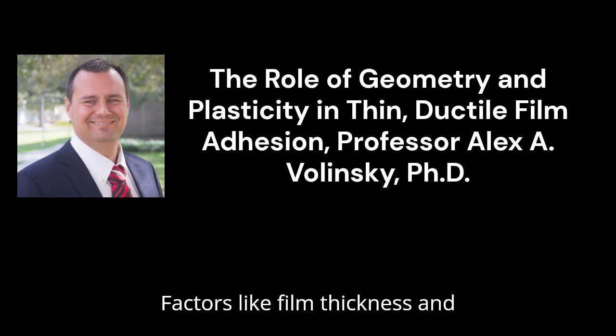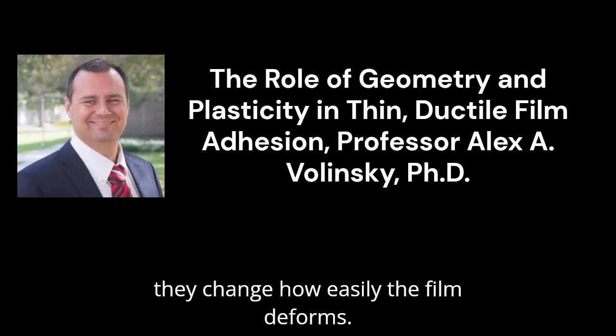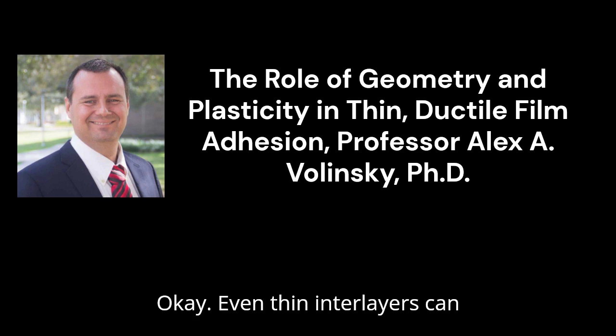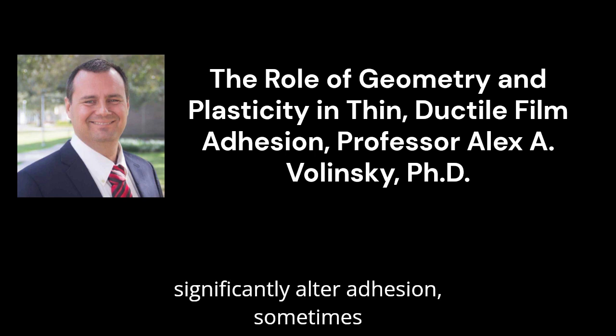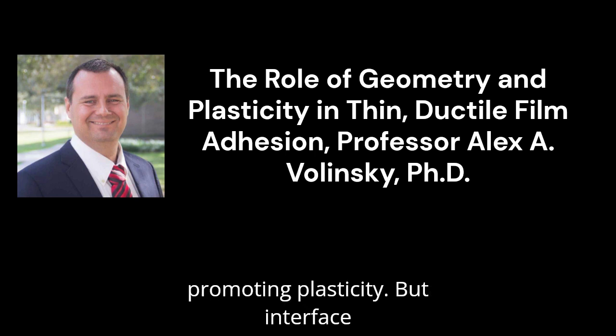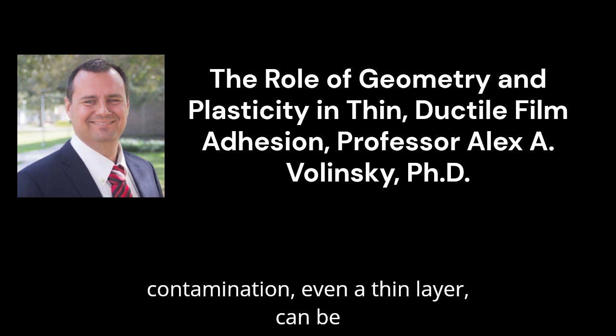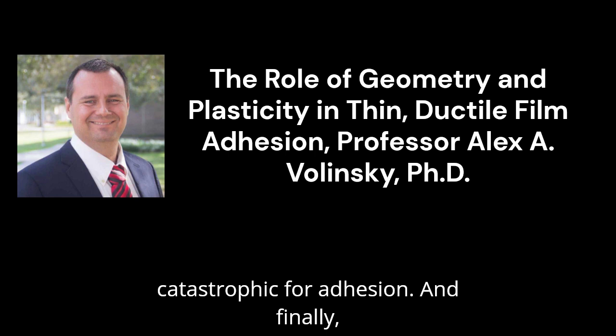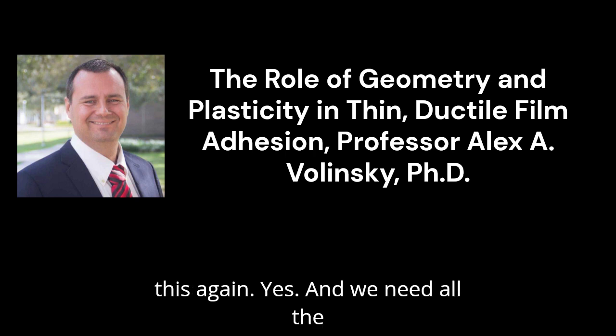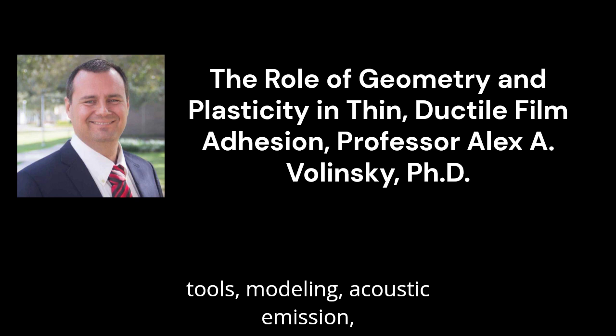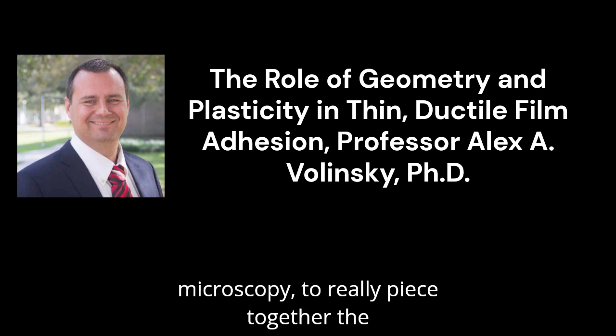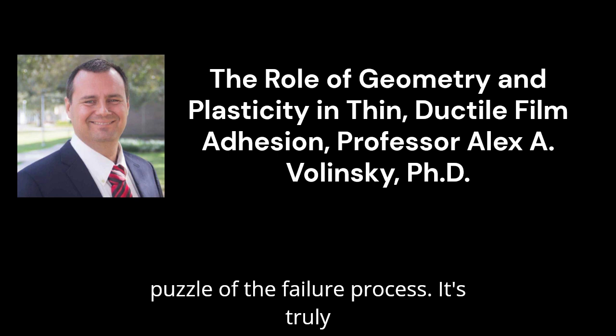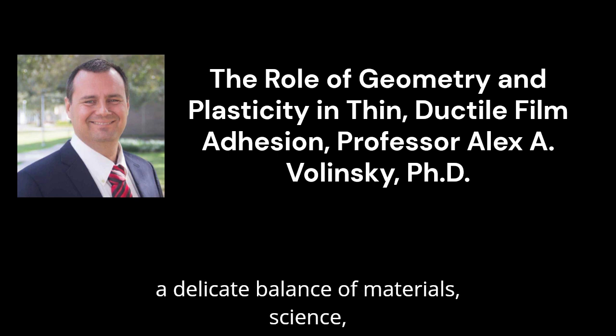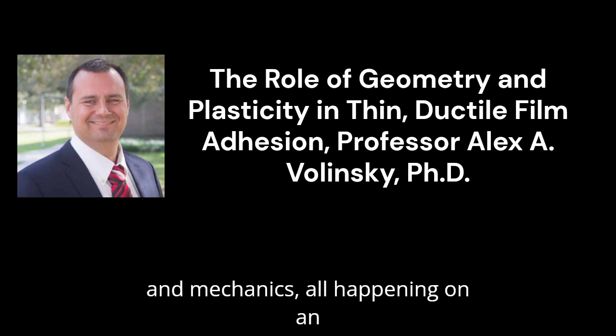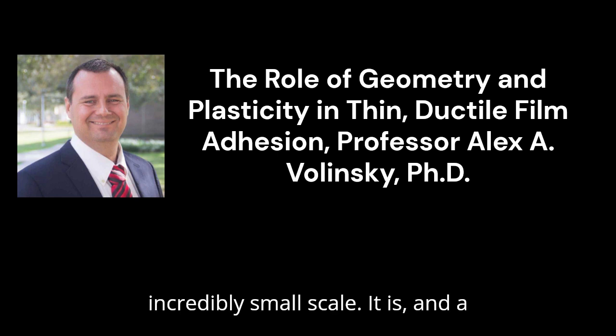Factors like film thickness and temperature have a huge impact because they change how easily the film deforms. Even thin interlayers can significantly alter adhesion, sometimes beneficially like the titanium by promoting plasticity, but interface contamination, even a thin layer, can be catastrophic for adhesion. Yes. And we need all the tools, modeling, acoustic emission, microscopy, to really piece together the puzzle of the failure process. It's truly a delicate balance of materials, science, and mechanics, all happening on an incredibly small scale. It is, and a complex one.